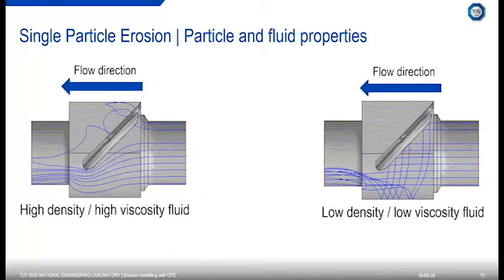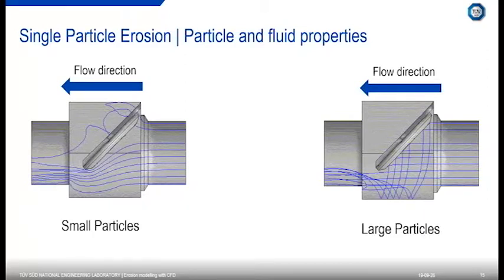Whereas on the right-hand image, we have a low viscosity, low density fluid. So the particle will now have a high inertia and is likely to detach from the flow. So it will continue along its initial trajectory and impact the wall, therefore potentially causing a region of erosive wear, and that's shown on the right-hand image. Now we can do the same image, but we can keep the actual properties of the fluid the same. So if we consider a fixed density and viscosity of the fluid, but now this time we alter the particle